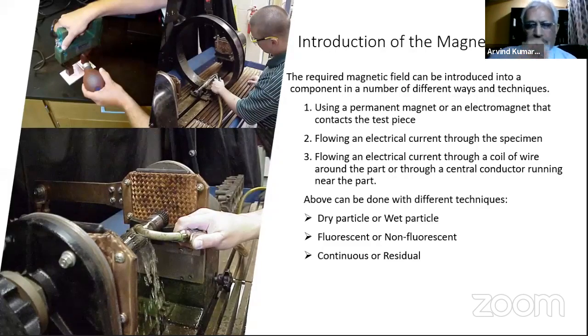Now you can do MT by using a permanent magnet, or using an AC/DC yoke, or by passing a current through a conductor, and you have coils where you can introduce magnetic fields. We will see them one by one. But for all of these, you have a dry particle or wet particle method, or a fluorescent and non-fluorescent method, and you have a continuous and residual method. Now we should understand what these are. Dry and wet we know, like in PT. We know fluorescent and non-fluorescent also. Now continuous and residual, this we should try to understand. What is a continuous method of magnetization and what is a residual method of magnetization, and where to apply which. Most of the applications we would be applying only the continuous method.